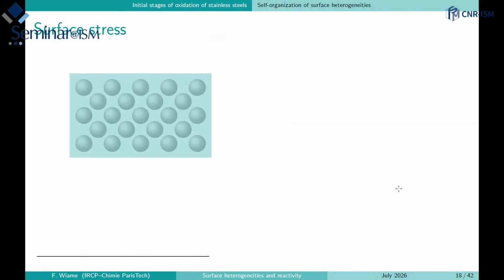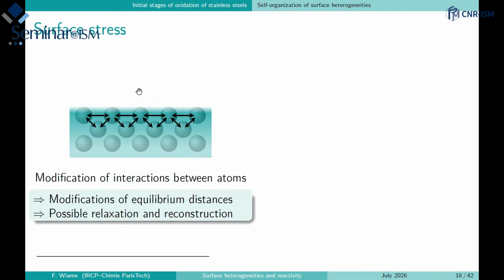And we can understand why we have self-organization, which in this case is slightly different from the self-organization of clouds, but here the self-organization is due to the surface stress that is created when a surface is created. So if you imagine, for example, that we have a metal with a homogeneous electron density and the positive ions, infinite in any direction, and we cut the sample into 2 to create a surface, then there will be a rearrangement of the electrons at the surface that will increase, in the case of a metal, the interaction between the atoms. And so it will change the equilibrium distance, it will change the lattice parameter at the surface.